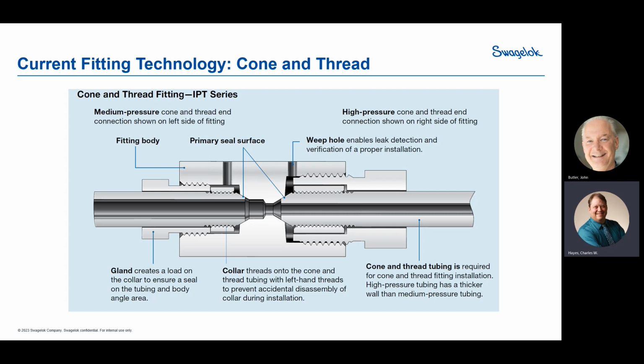The reality is that the cones are typically at a sharper angle than what the body is. So what we see is you will have things like a cone at 59 degrees and a body at 61. If you have a sharp cone going into a shallow body, then the nose of that angle is going to hit and create a single line of contact to make your seal. That's good, because one last piece that makes a good seal is stress concentration. However, it's only a single line. So you don't have that long L, you don't have that arduous path.